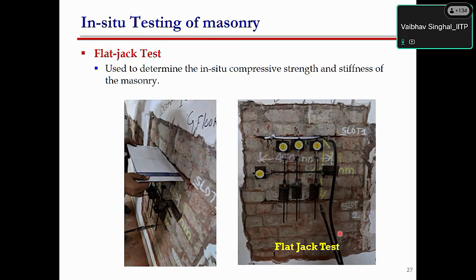So this test can give you the compressive strength, and the elastic modulus of the masonry present at the site. So this is a very good test. Of course, slightly difficult to do. You have to cut the slot and then you have to insert these flat jacks, and these flat jacks can only be used not more than 3-4 times, because when they get inflated and due to the permanent deformation, you cannot reuse them again and again.